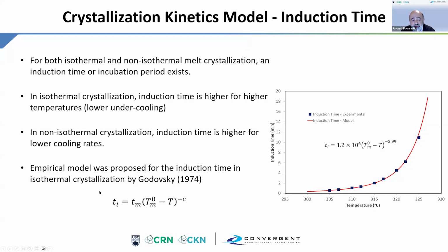The way we deal with this is there was an empirical model proposed for induction time all the way back to the 1970s. We use that, and we then chunk it so we can do non-isothermals. And you can see here, for example, on the right, induction time versus temperature, and you can see how the induction time is very small at low temperatures, but it becomes quite appreciable at high temperatures.